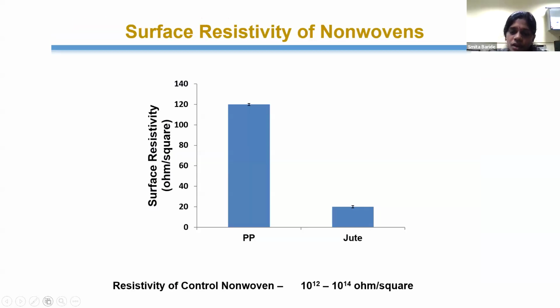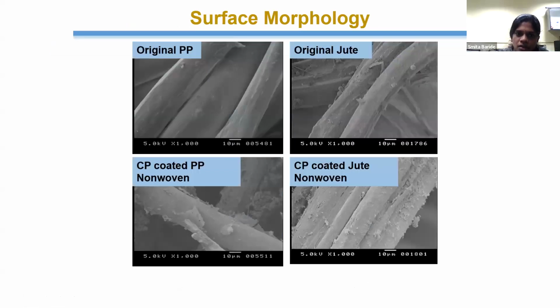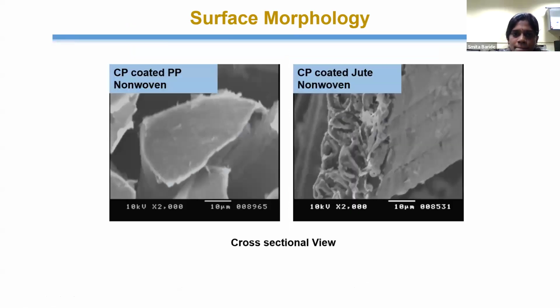Also, we have done the coating over non-woven samples, and the lowest resistivity we could achieve there is 20 ohms per square with the jute, and with the same formulation in the case of PP we are able to achieve up to 120 ohms per square. Here we can see the uniform deposition of polymer over this non-woven sample.